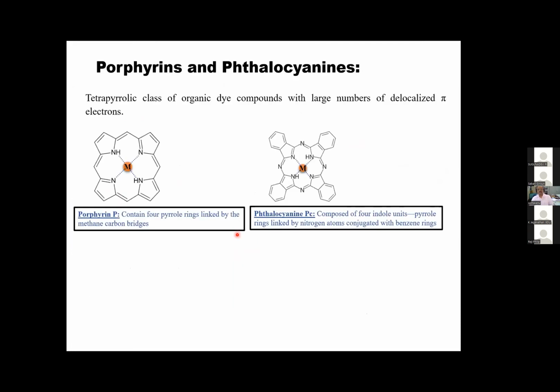So we start with some new materials. These are what we call porphyrins and phthalocyanines. These are large organic molecules where you have a large number of pi electrons, what we call loosely bound electrons. Sigma electrons are strongly bound, and in this kind of a system, this is a porphyrin, this is a phthalocyanine. A lot of pi electrons are there, which means they can be easily polarized when you put in a laser light, because of which you see a strong nonlinearity.